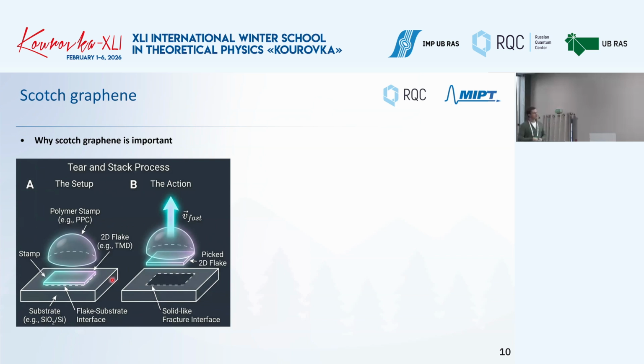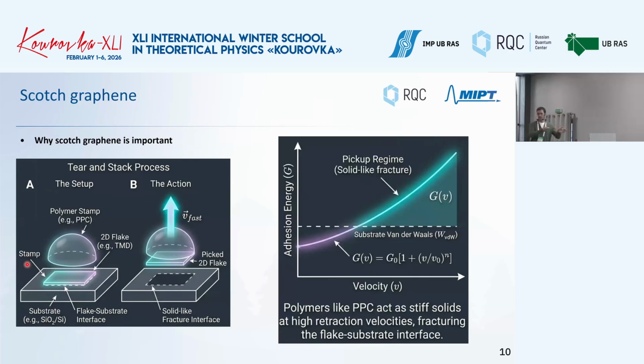So they have the polymer stamp. There is your flake of interest, and then you put your polymer on top, and it depends on the speed at which you detach this polymer. So you must have the ability to touch the 2D material and the ability to remove it away from the material with your, let's say, polymer stamp. And here are the formulas. I know the formulas are very important, so here I try to introduce as many formulas as possible.